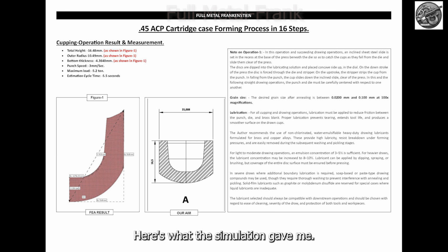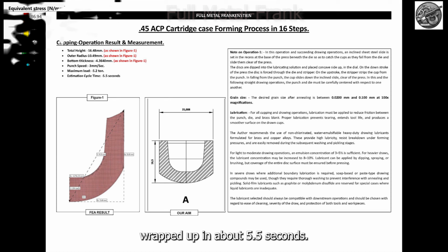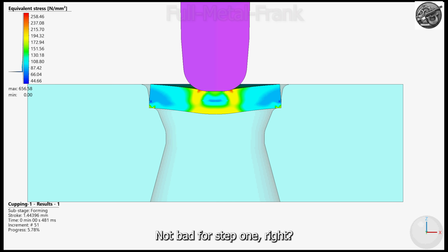Here's what the simulation gave me. Final cup radius, 10.49 millimeters, bottom thickness, 4.3640 millimeters, total height achieved, 16.48 millimeters, punch speed was set at 3 millimeters per second, maximum load required, 5.2 tons, and the whole cycle wrapped up in about 5.5 seconds. Not bad for step 1, right?